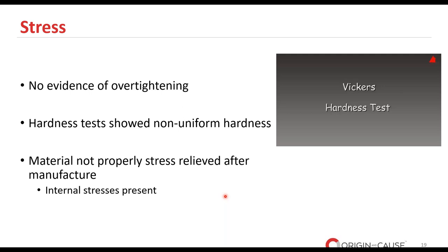Beginning with the installation, a common point of concern, as I mentioned before, was over-tightening, but we found no evidence of this. And this removes one of the more frequently observed stress contributors. But on the other hand, we performed hardness tests. And when we did this, we noticed an inconsistency.